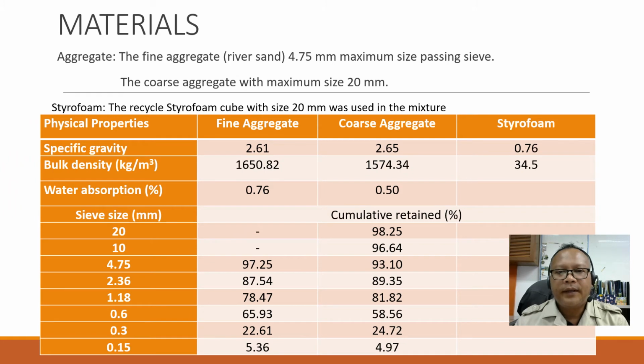For the aggregate, we use fine aggregate or sand with 4.75 mm maximum size, and coarse aggregate with maximum size 20 mm. For the styrofoam, the recycled styrofoam cube with size 20 mm is used, as in this picture. If we look at the table, for fine aggregate or sand, the specific gravity is 2.61, coarse aggregate 2.65, and styrofoam 0.76.